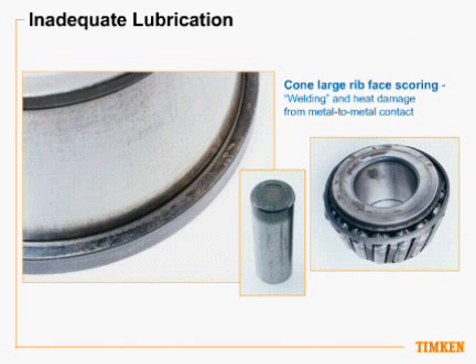Now, this damage is labeled as inadequate lube, but that doesn't mean that it was dry or didn't have any lubrication. It meant that the lube was not adequate to sustain the loads placed on the rib and roller contact area. This can be a result of excessive preload due to improper adjustment, which caused the rollers to slide instead of rotating. Or it can just be that the lubricant was insufficient or didn't have the right additives to suspend or sustain the load.